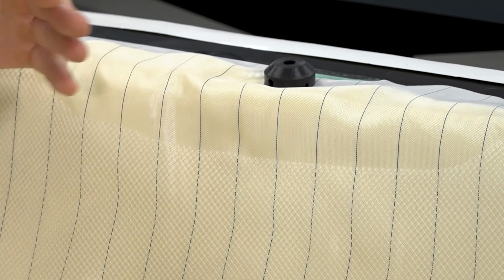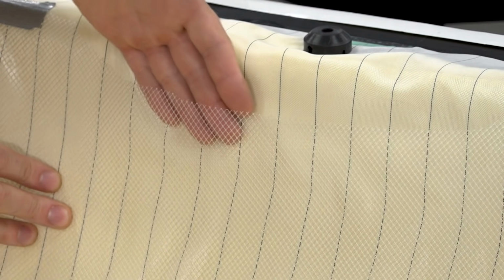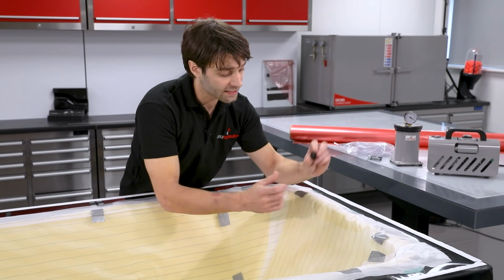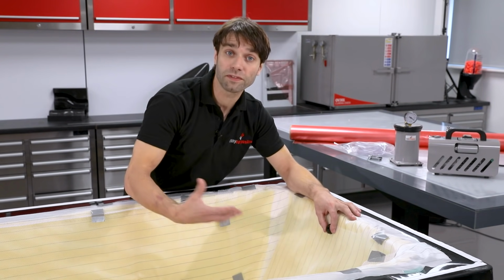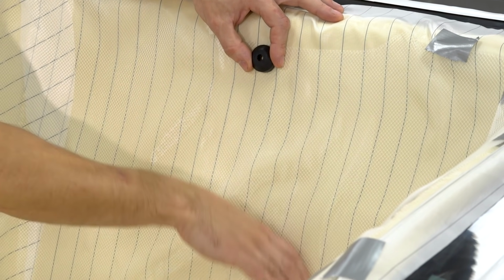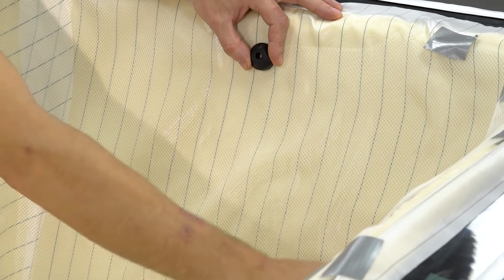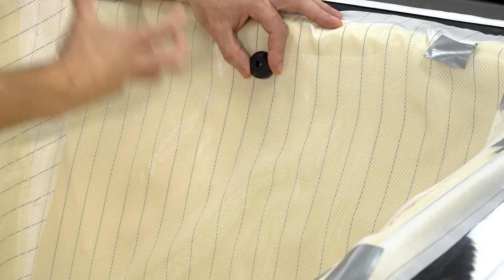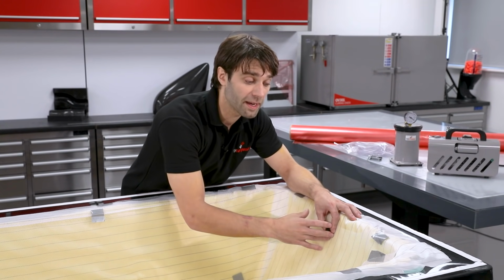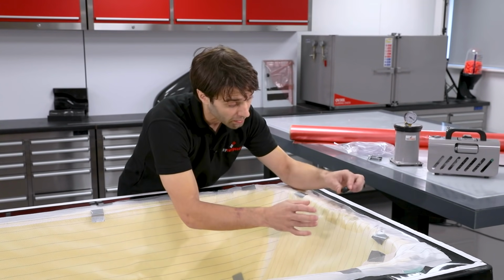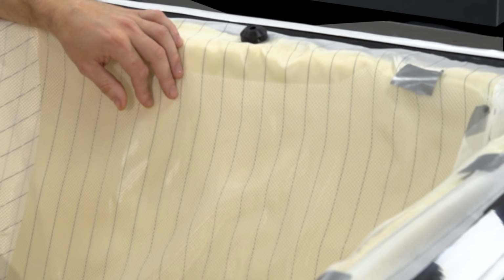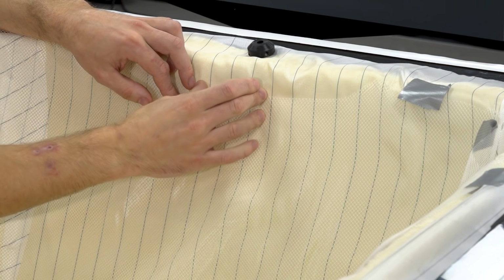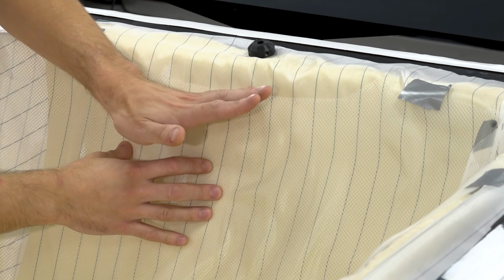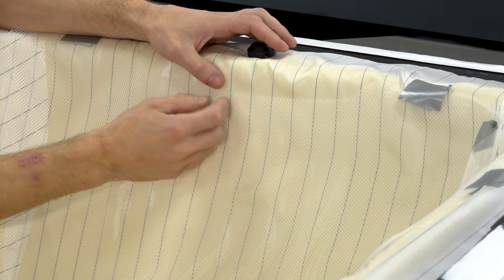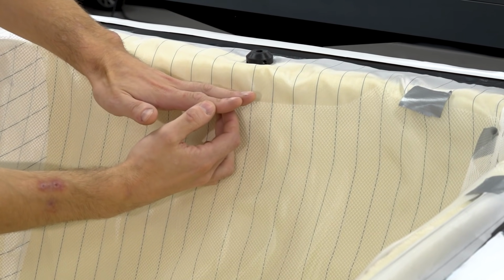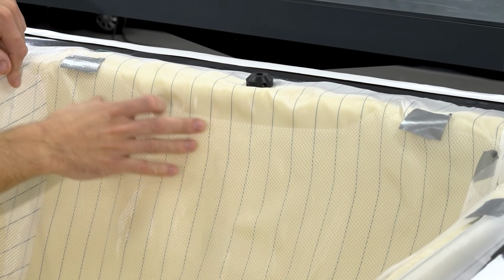I've also included something called a resin break. Now, that is where we've stopped the mesh short of the connector. And the reason for that is, if we were to put that connector on top of the mesh, and something unforeseen happened in the infusion and the flow path, and we ended up with the resin hitting this connector before, say, it infused these corners, so it's coming up in an arc like this, we would have to keep the vacuum running and keep drawing resin off just to maintain a vacuum on the dry areas. But by putting in this resin break, we have a situation where the resin will flow up to here, and if it does get to this point first, it is just like the resin's hitting the brakes, so it slows right down about 20 times. And that will give us time for the resin to start leveling out at the top here, and we'll be maintaining a vacuum into these dry areas.